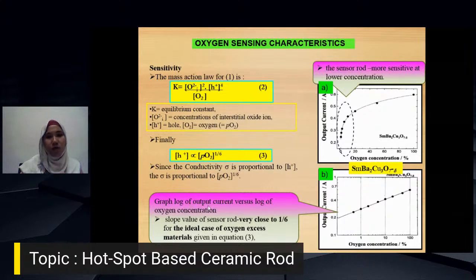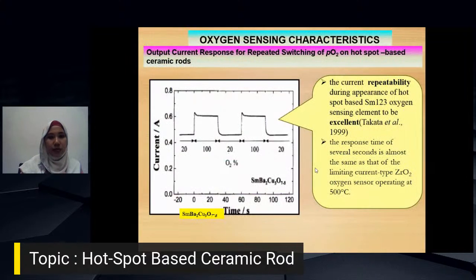So the graph of the log of the output current versus the log of the oxygen concentration. The slope value of the sensor is very close to 1/6 for the ideal case of the oxygen excess material, which is given by equation 3 here. The hole concentration is proportional to the oxygen partial pressure.